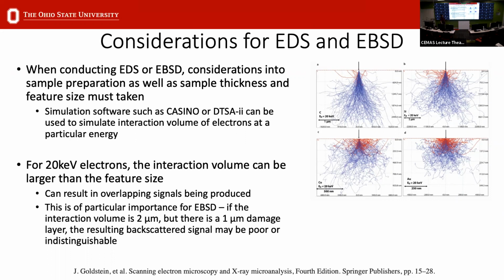And you can use a program such as Casino or DTSA to determine the trajectory of how deep these electrons interact into your sample. So when you're doing something like this, you want to consider your feature size because your interaction volume could be larger than the feature size. So if you're trying to do EDS, you might get mixed signals from deeper in the sample that also show up in your EDS. And this is especially important for EBSD and is a reason a lot of people have some issues getting good patterns. For example, if your interaction volume of your beam and your material is 2 microns, but there is 1 micron of damage in your damage layer, that's going to hinder your signal and you might not be able to distinguish the patterns.